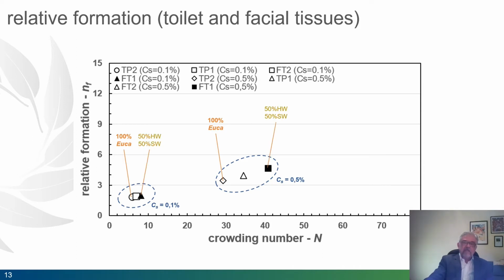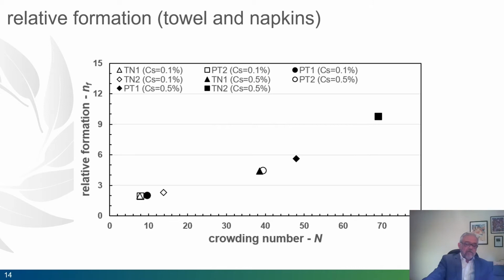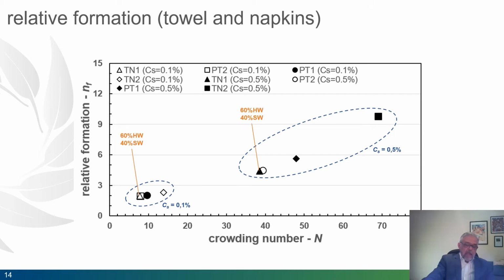In opposition, the highest crowding number and the highest relative formation index was found for the mixture of 50% hardwood and 50% softwood normally encountered in facial tissue production. In the results for towel and napkins, we can see a similar behavior. Furnishes containing hardwood in majority will show lower crowding numbers and lower relative formation indexes. On the other hand, furnishes containing softwood are those more prone to flocculation and formation unevenness, like tissue napkins and towel made of 100% pinus fibers.